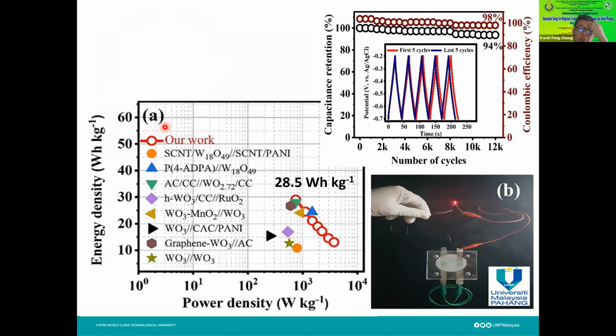And we run through the cycle test, which you can look at here. That is our prototype, whereby we put in the graphene and our tungsten oxide, and once we charge it up, we are able to power up the LED light. So that means there is energy storage happening in your supercapacitor, and then we calculate the amount of energy that we store. We found that it's 28.5 watt-hour per kg.